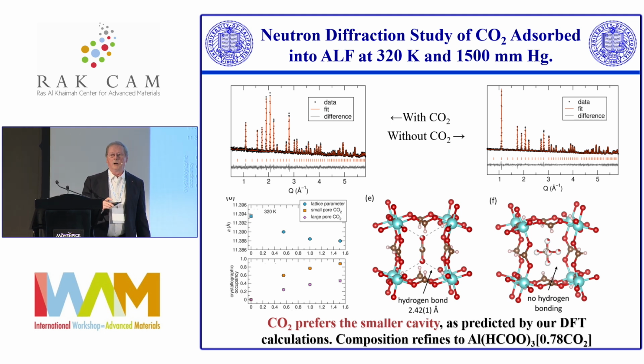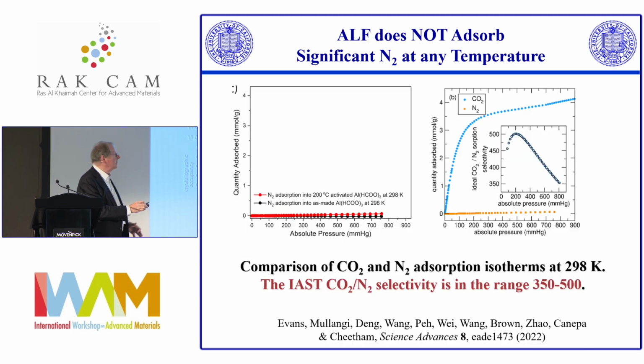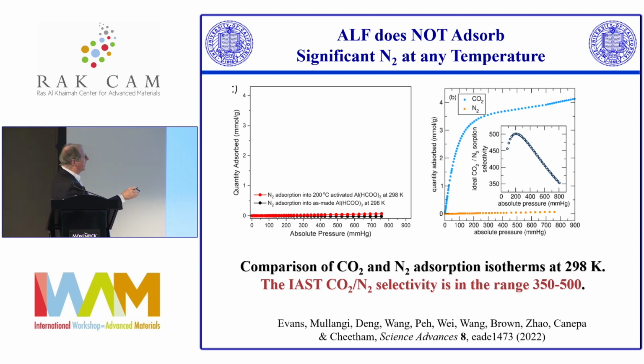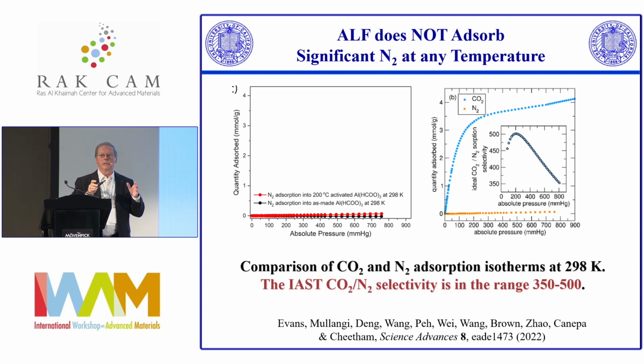You may wonder, why did we measure the surface area using CO2 isotherms? And the reason for that is we quickly realized that nitrogen won't go into this structure. Even though nitrogen is kind of minutely larger than CO2, it will not go into the structure. And so this is the nitrogen adsorption isotherm. The black one's the as-made material, and the red one's the activated. And so virtually no nitrogen goes into it. There's a little bit of leakage depending upon temperature.